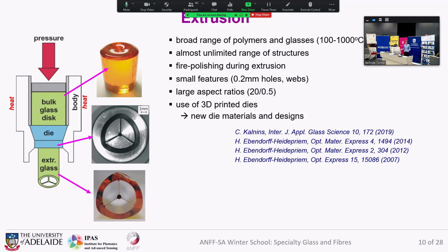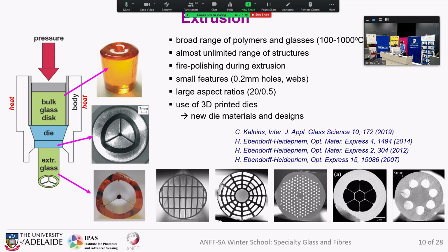And it allows an almost unlimited range of structures, which you hopefully can see from the photographs of these preforms. Nice thing is also because the glass is hot when it comes out of the die, it fire polishes, creates a smooth surface, which is always important for optical properties. We can make very small features, 0.2 millimeter already in the preform, large aspect ratios, preforms with 20 millimeter outer diameter and 0.5 millimeter hole size.